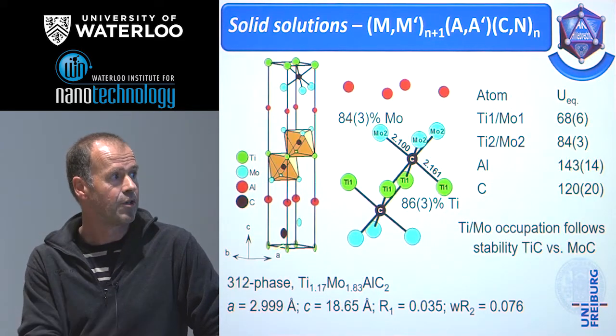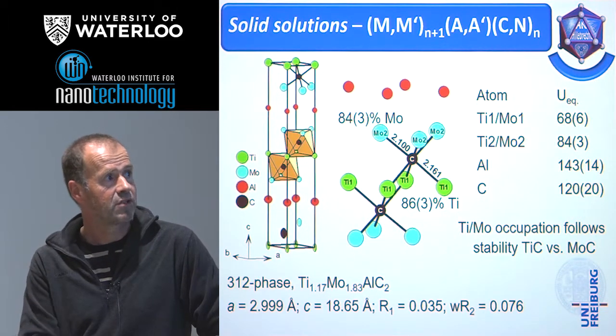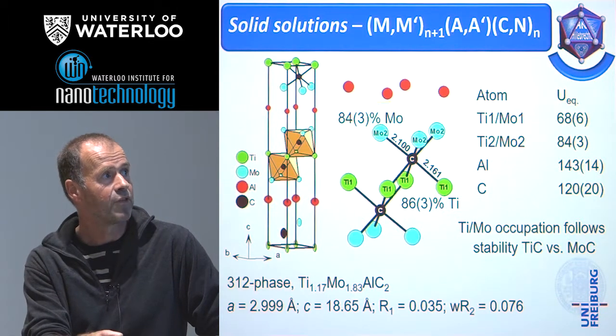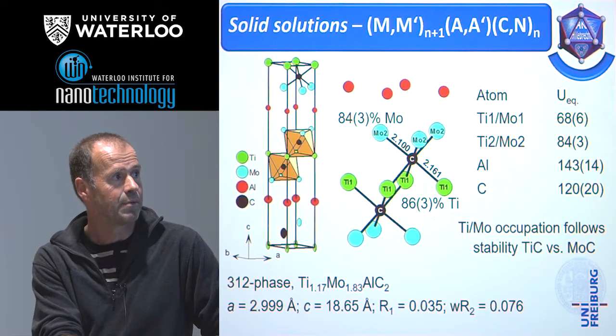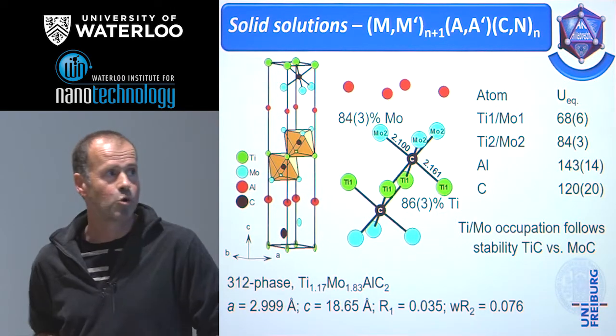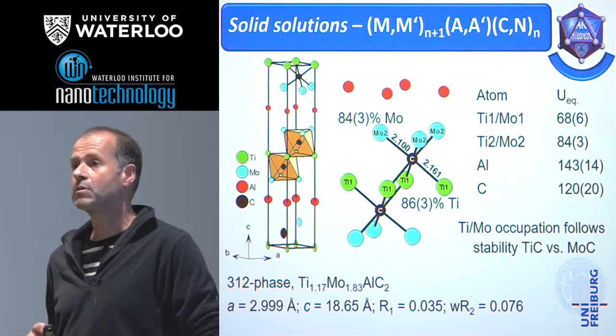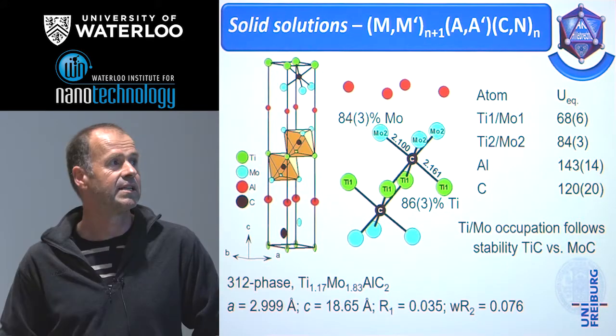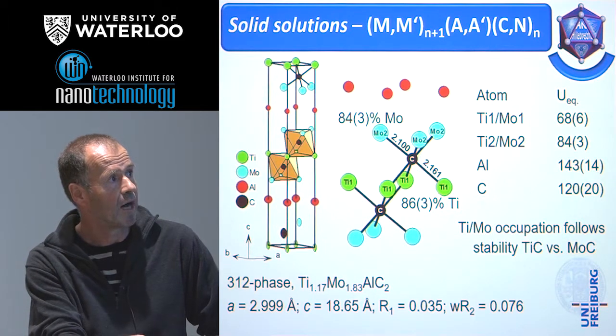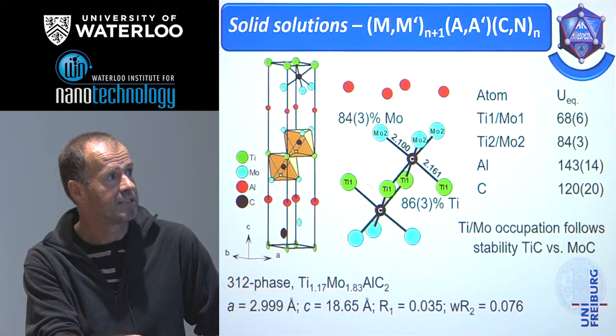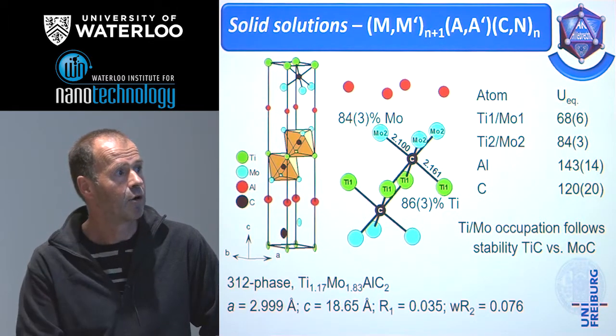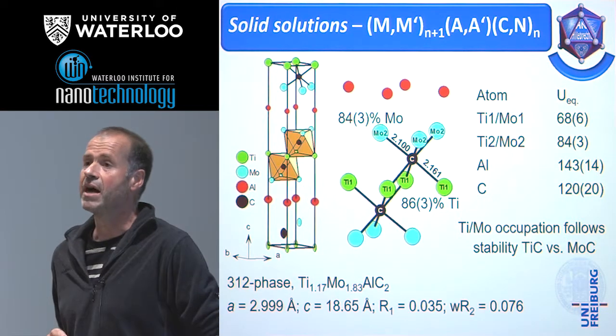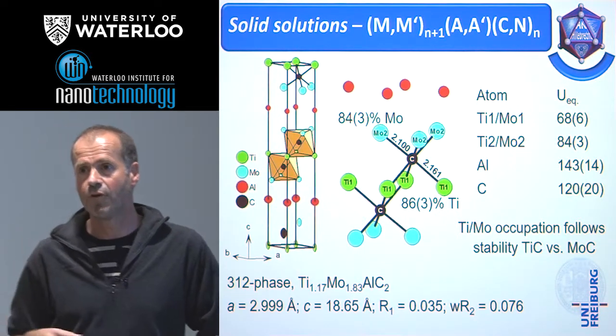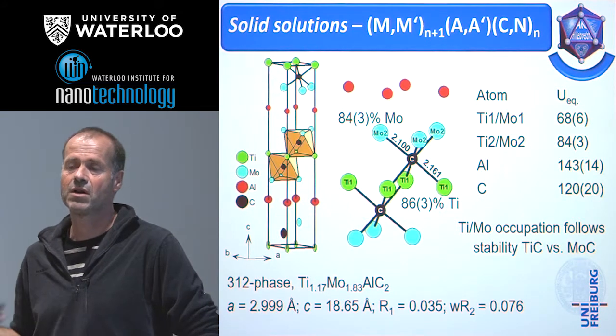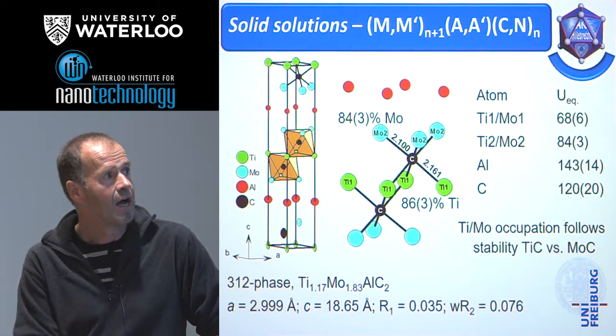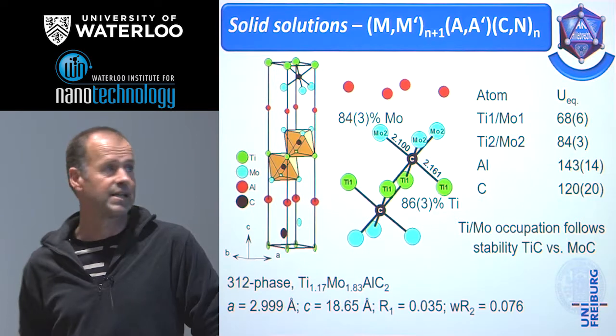deviation. And we could show that also the so-called 3-1-2 phase shows this asymmetry. We have a strong preference of the inner side by titanium and of the outer side by molybdenum, but because the multiplicities are not the same, we have again a deviation. This is quite normal, more or less. We know that titanium carbide is much more stable than molybdenum carbide, and obviously we prefer the higher coordination of the transition metal by carbon. This is the coordination number 6 by titanium, and here we have only 3 molybdenum-carbon contacts. This follows the well-known stability of the binary carbides. And for example, if you think about the use of these two-dimensional materials for catalytic processes or something like that, we can give you an idea how the transition metals prefer the different sites.